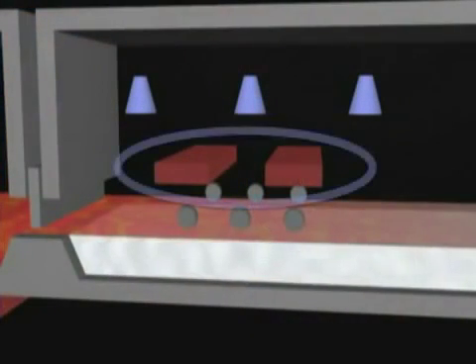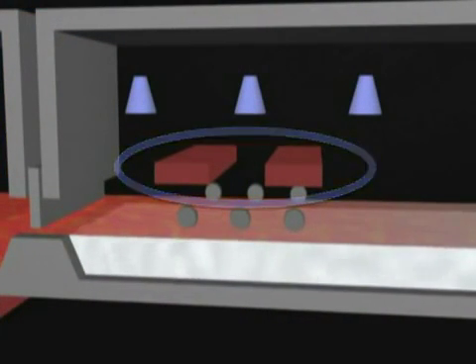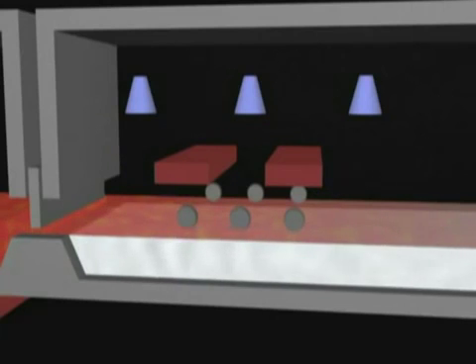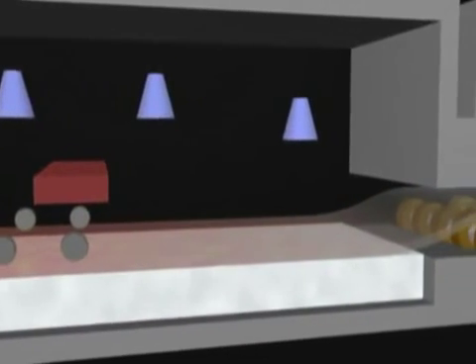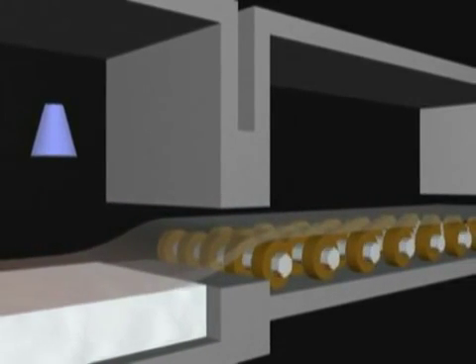Toothed wheels called stretch machines are used to further alter the glass ribbon's thickness and width. Heating elements located above the stretch machines also control the thickness of the glass as it moves through the bath to the exit end. Here, at its final width and thickness, the glass is cooled down by a series of water coolers and safely lifted from its tin bath onto the main line's conveyor.